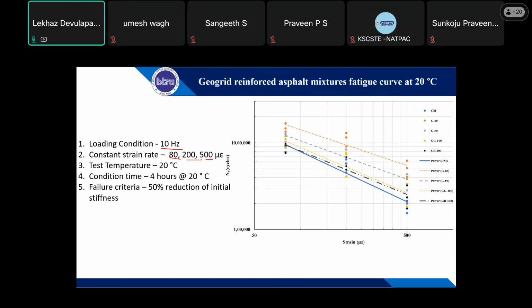The failure criteria we have chosen here is a 50% reduction from the initial stiffness. Initially the pavement will have a modulus of the stiffness value K. From that value, how many cycles it took to reach the 50% reduction. Suppose 2000 is your initial stiffness, how many cycles it has taken to reach the 1000